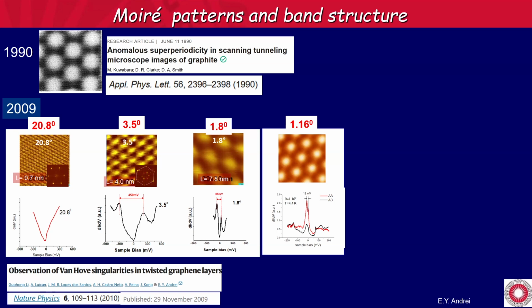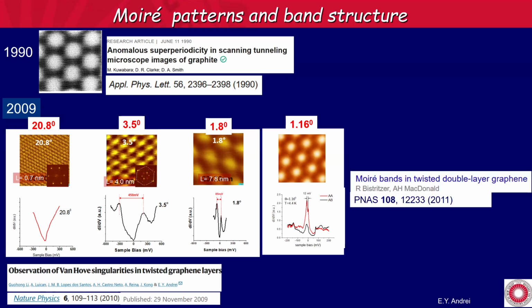And this is where Rafi and Allan came in, and then they showed, using what's now known as the chiral model, using tight binding, that you do indeed get these Van Hove singularities, and when they merge, they merge at this magic angle, now this iconic magic angle.